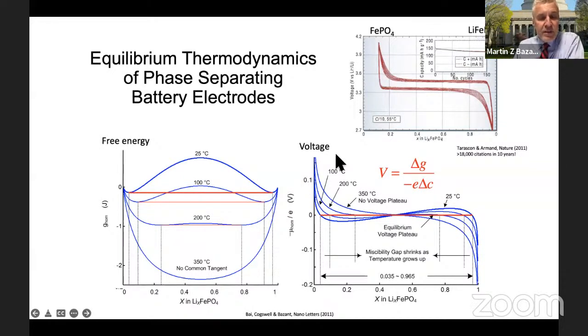And now the connection to electrochemistry is that the voltage at equilibrium, that would be the open circuit voltage, is the change in free energy resulting from that reaction per charge transferred. Mathematically, if the anode is not doing anything, and this is a cathode where the concentration is changing, then the voltage as a function of concentration is basically the derivative dG/dc, where c, or x, is the horizontal axis, but with a minus sign because the electron charge is negative. So basically, the blue curves on the right for the voltage are the derivatives of the blue curves on the left at different temperatures. And the red line, which is the plateau, corresponds to a plateau in voltage. So now you can understand that at the endpoints of that plateau are two stable phases. What I'm showing you here is very well understood by materials scientists and electrochemists, and it's one of the ways that they map out the phase diagram in composition of various electrochemical materials or battery materials.